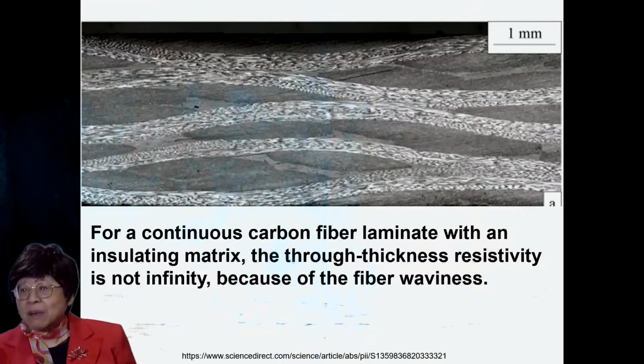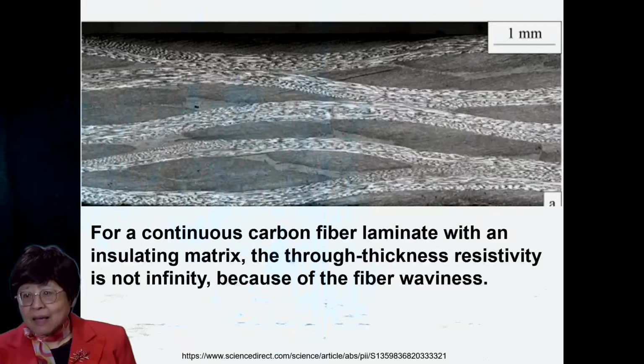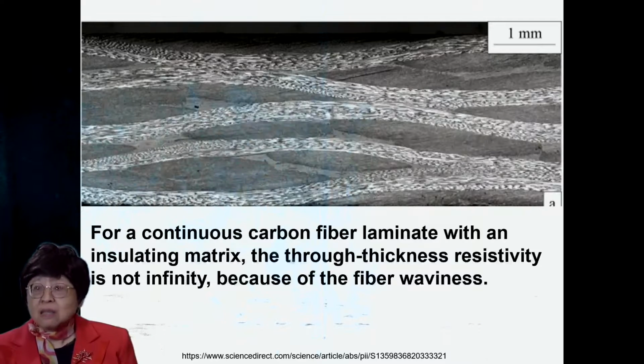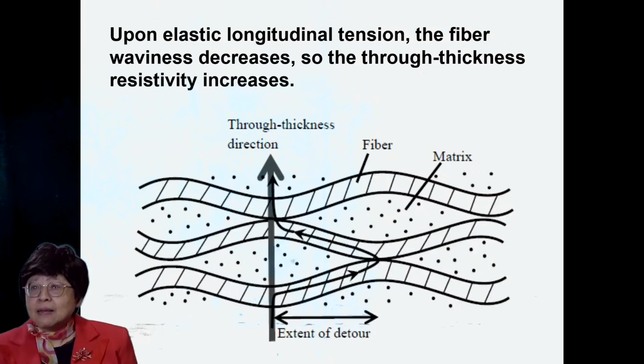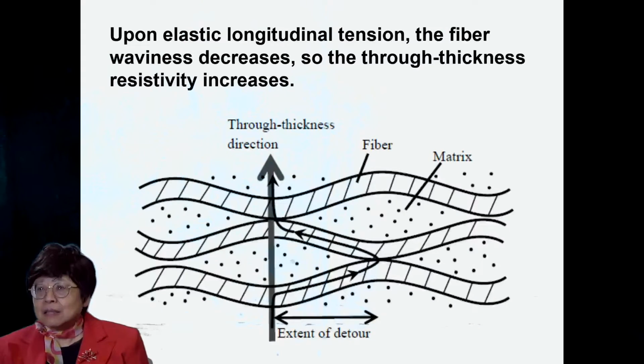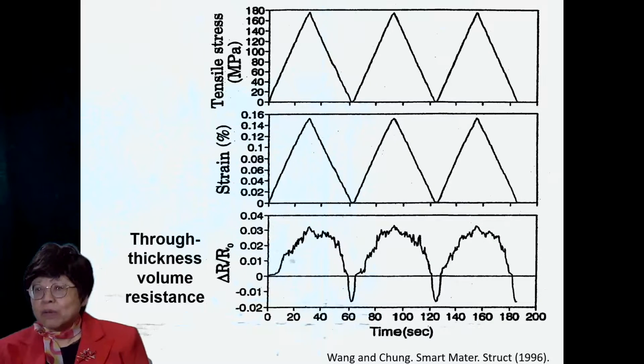Now, for a continuous fiber laminate, the carbon fiber is conductive, but the matrix, a polymer like epoxy, is not conductive. In spite of that, the through-thickness resistivity is never infinity, and that is because of the fiber waviness, which causes fiber-fiber contact. So upon elastic longitudinal tension, that is horizontal tension in this picture, the fiber waviness decreases, so the through-thickness resistivity increases. And that's exactly what we see for the through-thickness volume resistance at the bottom here. That resistance indeed increases every time one tensions it in the horizontal direction.